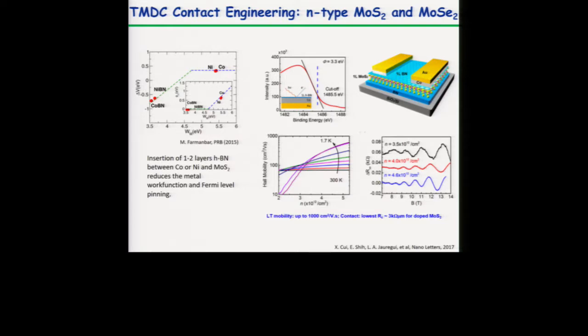And in single layer MoS2, we were also able to obtain Shubnikov-de Haas oscillations at low temperature. But as I say, they are mostly limited by charge impurity scattering. Once we reduce the carrier density, mobility also goes down. So it's hard to reach lower carrier density dominated transport in MoS2. But we can get good contacts out of it.